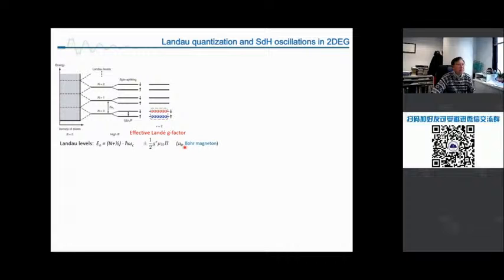That represent the electron interactions in states. So if there's no interactions, it's just a simple particle picture of the particles, then the G factor is 2. That means the separation between the up and down state is just mu B, where mu is the Bohr magneton. It's a constant. But if something unusual happens in the states, the G factor should be very large, or very small, but normally it's very large.